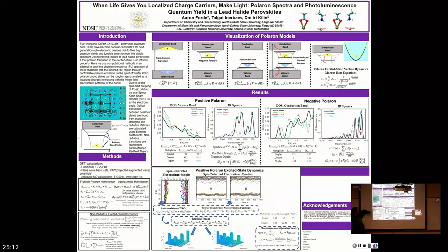And that's what happens in space. And then for the polaron formation, polarons have bound states. And in the spirit of Wannier-Mott, you can approximate those bound states as the electron interacting with the average ionic charge that's moved around it. So it's kind of like the Coulomb interaction. You can see the energy spacings will ideally follow the same type of trend. We have our electron at the lowest bound state, and then the bound states take on hydrogenic wave character.